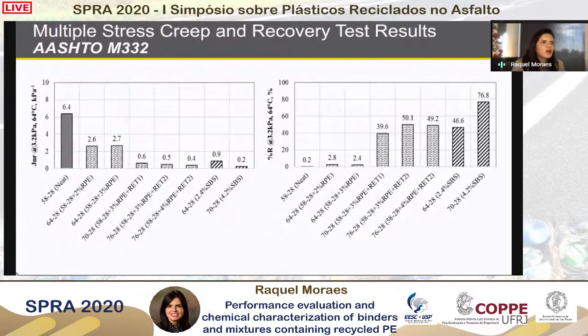In terms of the percentage recovery, we can see that the 2 and 3% binders modified with the recycled plastics had almost negligible percentage recovery at 3.2 kPa stress level at 64 C. On the other hand, the 3 recycled plastics modifying binders that contain the terpolymer used as compatibilizer had an improvement in the percentage recovered. And to mention, in comparison with the 70-28 binder that was modified with 4.2% SBS, that one was the one with the high elastic recovery due to the elastomeric nature of the additive.